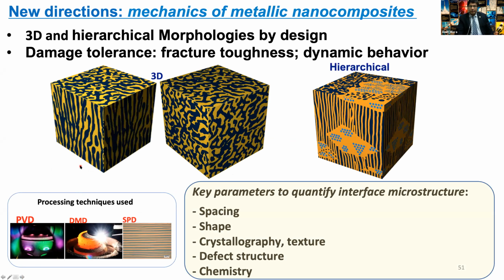microstructures are the key. And I think regardless of what kinds of materials you are studying, the properties are driven by the microstructures and the defect microstructures going way beyond the chemical composition. And even with the same chemical composition, we can change the microstructure that traditionally has been studied primarily by a single parameter such as grain size or with texture. We can now begin to bring in the shape and the multitude of shapes and the hierarchy of interfaces and the defect structures, which is again a very promising area for material science in this field.